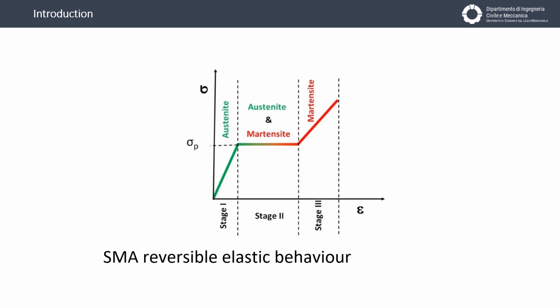Now, in this slide, you can see a schema of mechanical behavior of shape memory alloys. You can see three different stages. The first one, stage 1, is characterized by a linear elastic behavior, which has slope, which is the Young modulus of the austenite. Austenite is the lower phase, initial phase of this material.